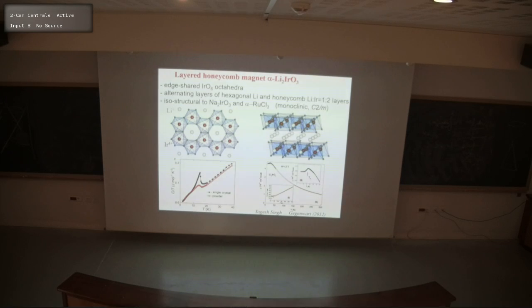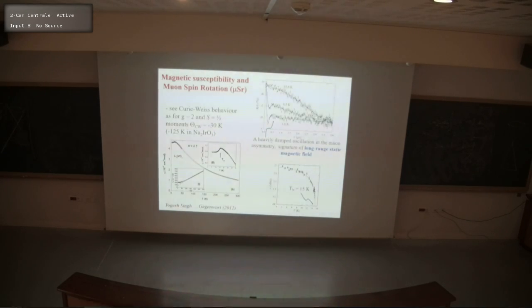So here are heat capacity measurements to show that there is an anomaly associated with the phase transition, which actually has magnetic character. These are susceptibility measurements. And through muon spin rotation, it's also observed that there's a local field that develops as an order parameter below the heat capacity anomaly. These oscillations in the muon signal indicate that there is a net local field that's generated.